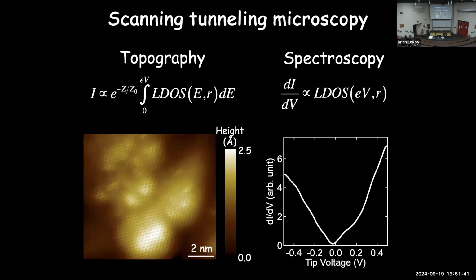The other mode we can operate in is, instead of this topographic mode where we're scanning with a constant current, we can go to a fixed location. We turn off that feedback circuit, but we keep the tip height fixed. We keep Z fixed, and we change the voltage. So we change the V here. And that's going to change how many states we're integrating over. If we then look at how that current changes as we change this voltage, well, that's the derivative of this. That's giving us basically this local density of states information. So that's giving us the number of states which are available for tunneling at that position as a function of energy. And so that's what is shown here.